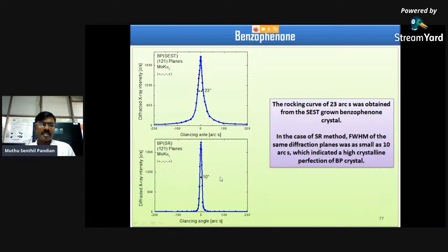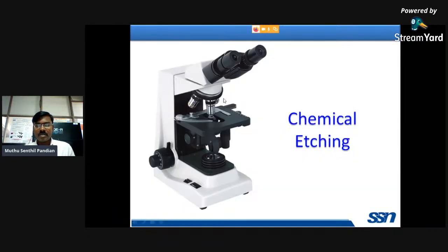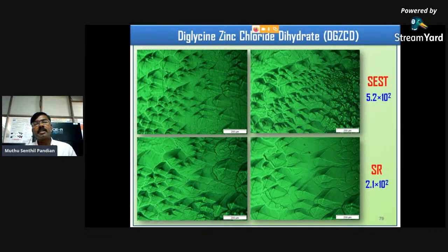This is a very perfect crystal, and this is the conventional method grown crystal. So chemical etching is an important and powerful tool to identify the dislocation content present in the conventional and SR method grown crystal. This is for diglycine zinc chloride single crystal. This is for conventional method.